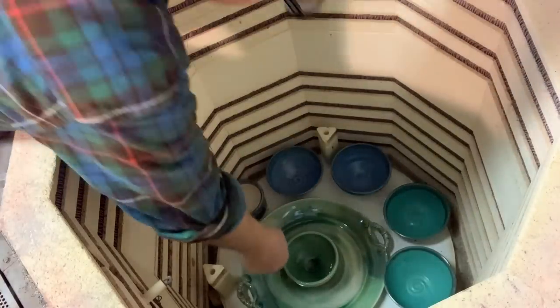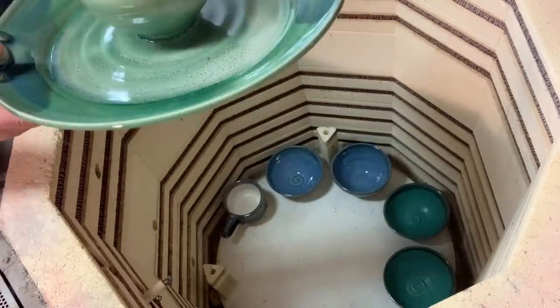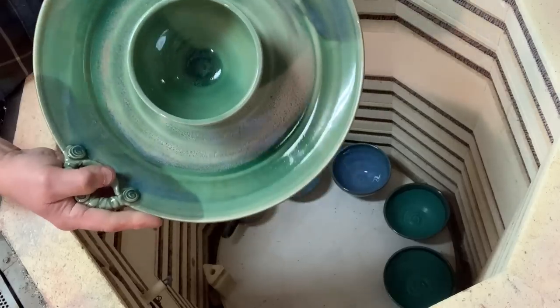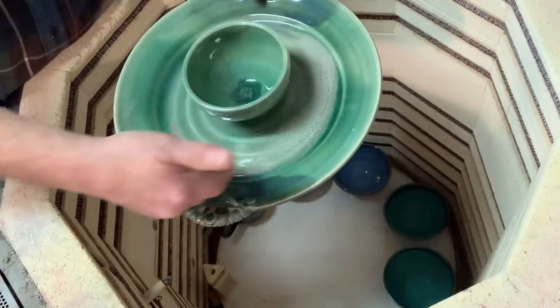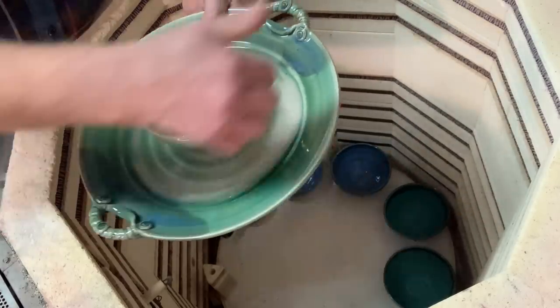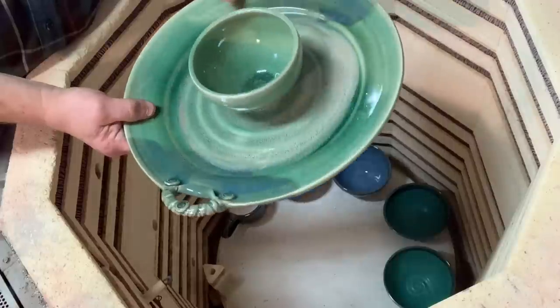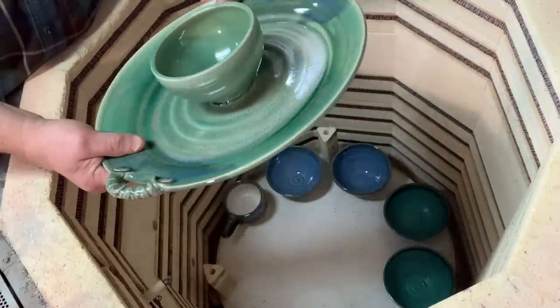Last layer down in the kiln - this was a refire. I refired this piece because it had a little bit of crawling on it, and it turned out really good. We've got nice crystals in the middle there. What I did is dip it with variegated blue over the chun green that way and that way, then a sweep of oatmeal. They've blended and melted in the middle and you've got all those crystals formed - a really nice surprise since it didn't work the first time.